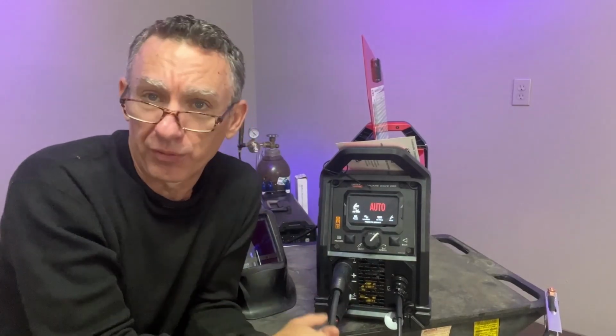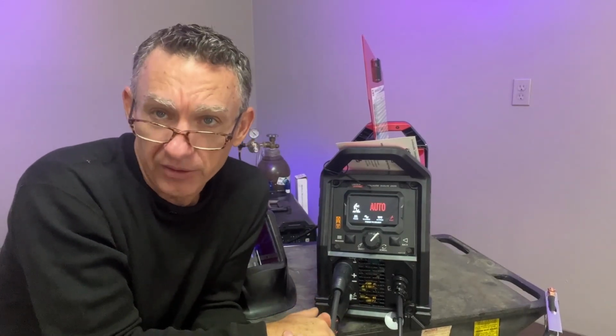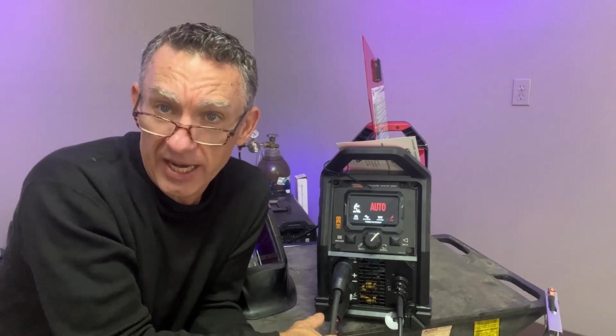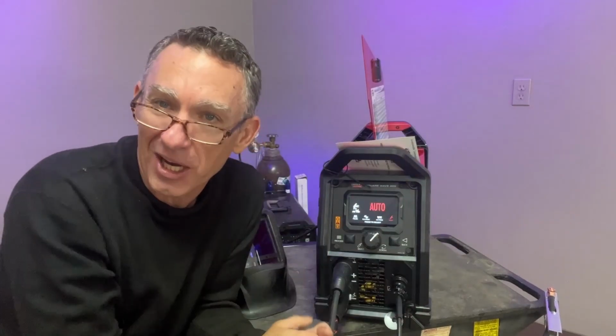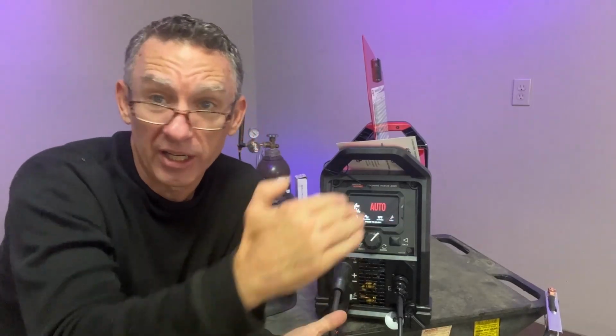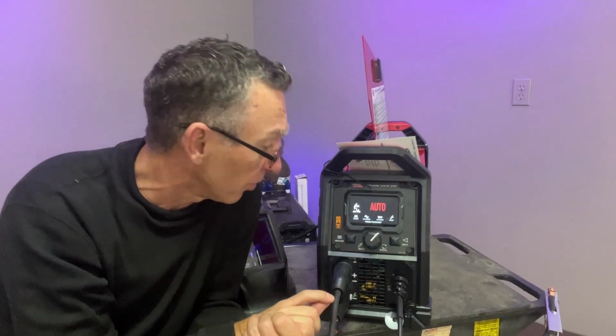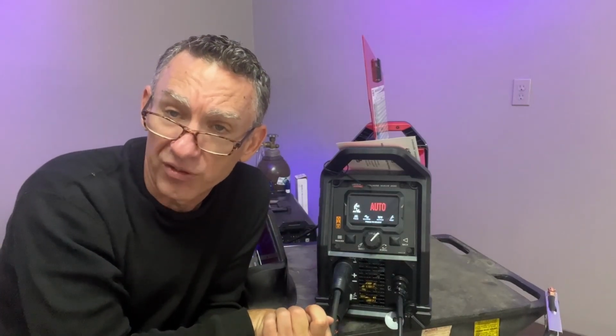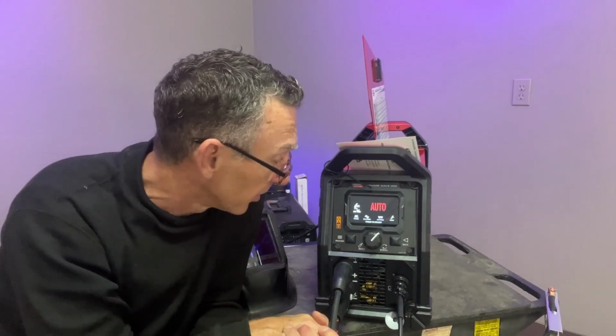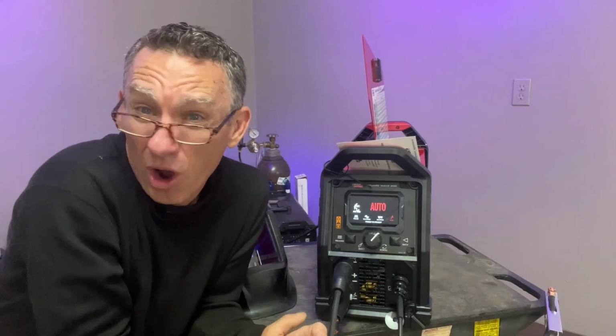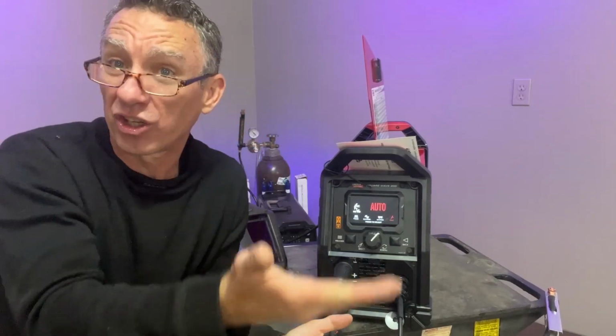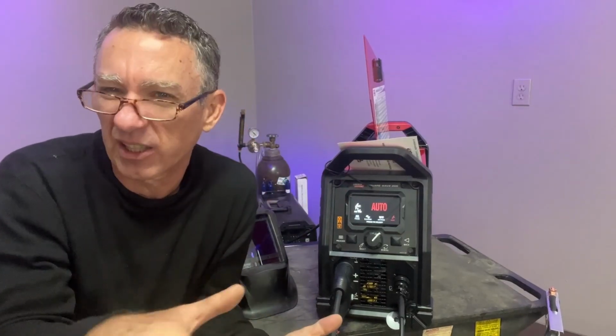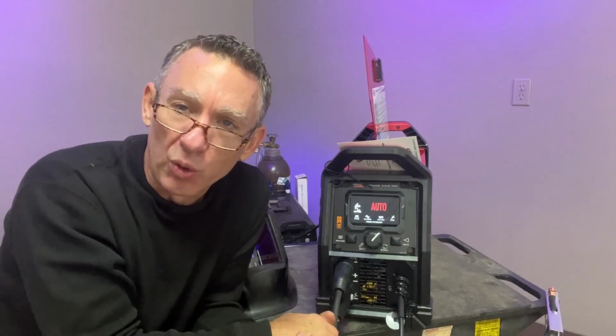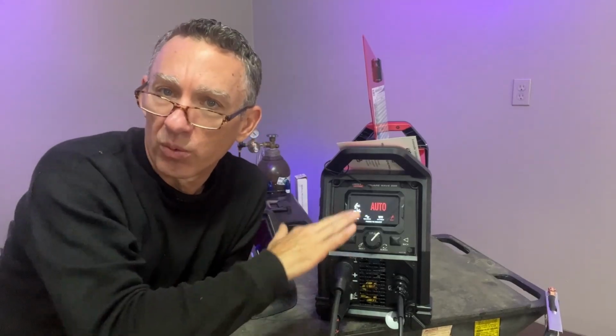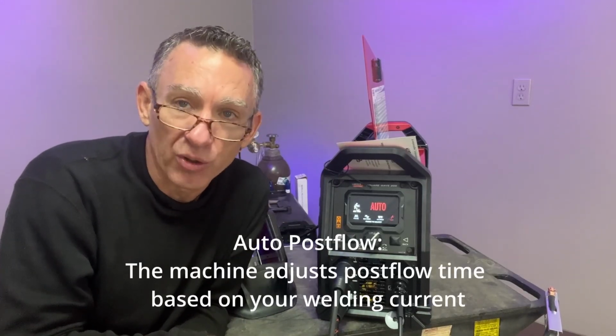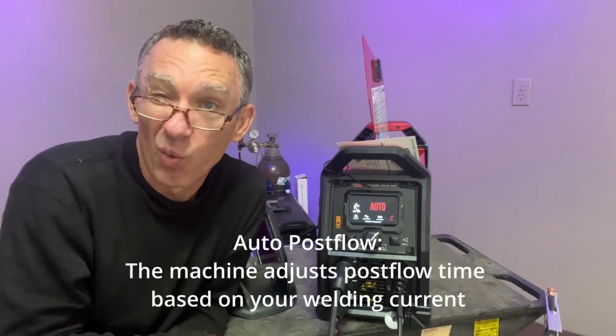So automatic post flow gives you a minimum of 5 seconds, and then for every additional 10 amps that you weld, it starts to tack on another second. So you'll have a minimum of 5, and as you get up to 100 amps, boom, it's going to automatically adjust your post flow, and it's going to give you 10 seconds, which is appropriate to protect your tungsten and the weld. At the end of the day, you can set it and forget it, put it in auto. If I go up to 200 amps, that thing's going to crank up and give me 20 seconds of post flow, theoretically in that ballpark. So that's kind of a cool thing. You can go high to low. You don't have to worry about readjusting your post flow to optimize your gas, prevent smoking your tungsten, and yet you're not going to waste it, right?